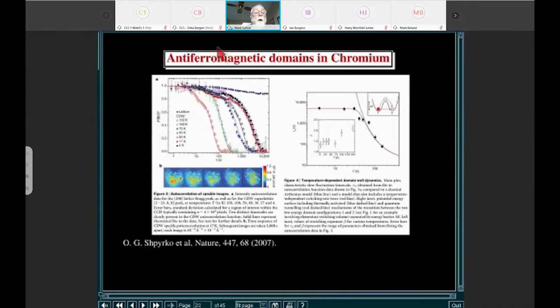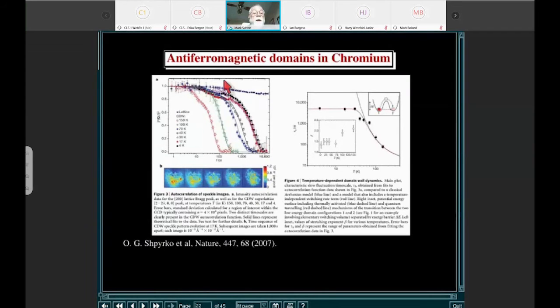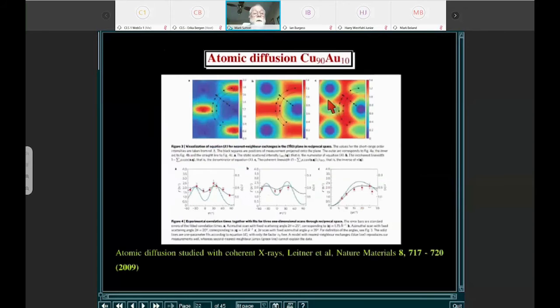Here's an example where you can see the structural effects of the antiferromagnetic domains in chromium, and you can now do XPCS measurements, which has quite a structure. The interesting fact here is as you lower the temperature, you reach a region where they argued in the paper that this is the zero-point motion of the fluctuations of the antiphase domain walls in chromium, which get saturated, which you can see at small angle scattering, low temperatures, because that's all that's left.